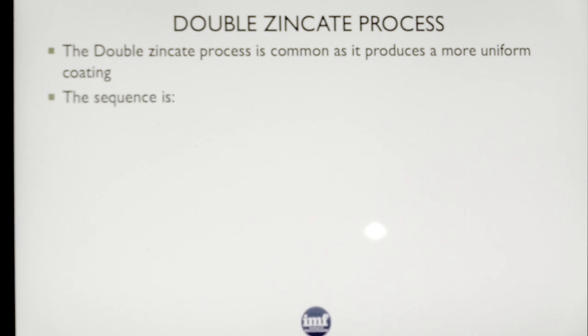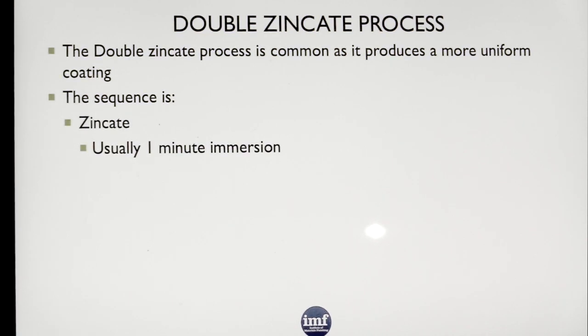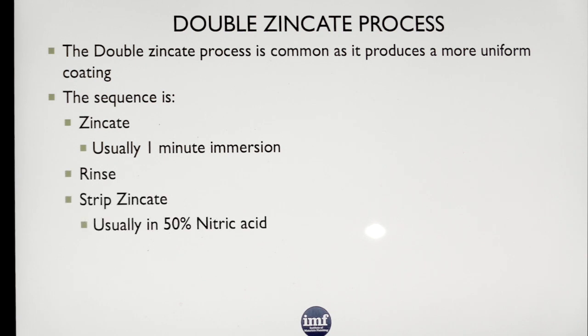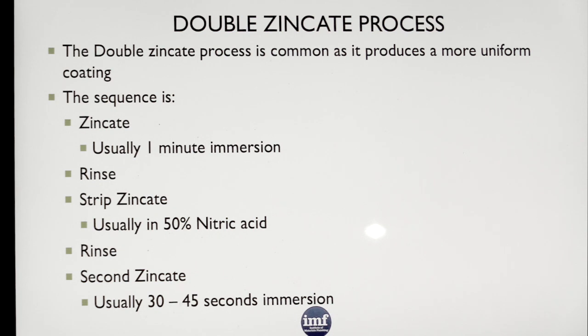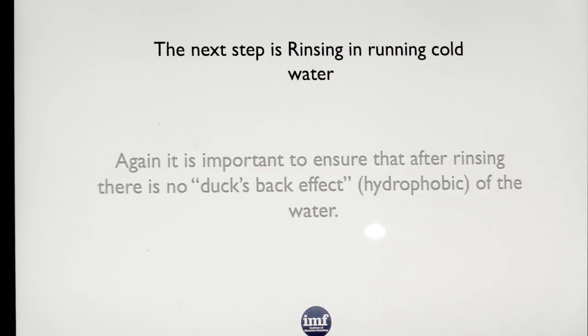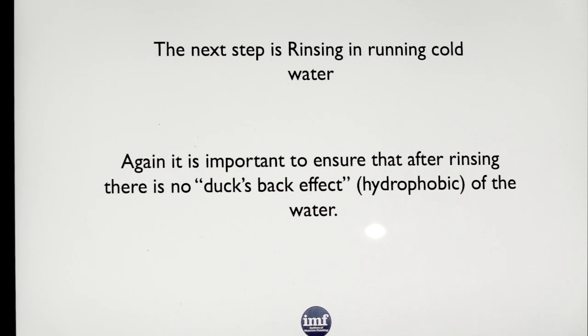So you get the sequence of zincate, usually 1 minute immersion, that's your first one. A rinse, strip the zincate, usually again in nitric acid, a rinse, and then you zincate it again. This time between about 30 and 45 seconds. And what you should end up with is, you can take these out by all means, don't worry about handling them if you want to, but you can see now that there is a grey coating of zinc on that particular piece of aluminium. And that is what we're now going to plate onto. So effectively we're plating onto a zinc coated aluminium. Rinse again. You must make sure that there's no grease or anything, otherwise you can get bad adhesion.